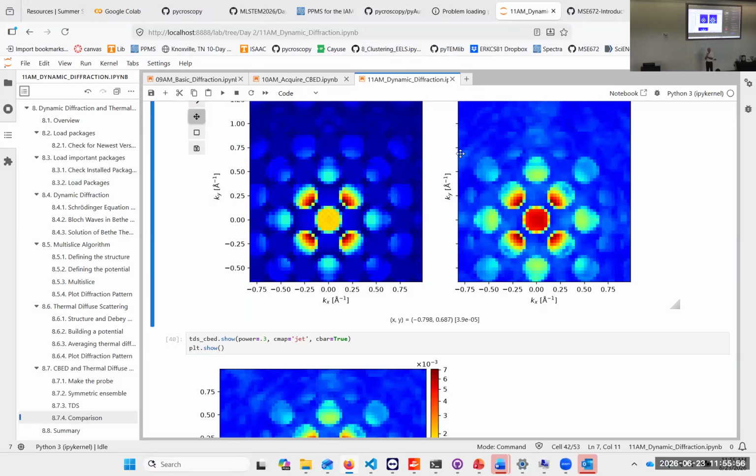At least in ABTEM, you can make it very, very sophisticated. You can use potentials from density functional theory. You can have that calculated, and then with molecular dynamics, you calculate the phonon dispersion, and then you can get that extremely close and see which kind of things contribute most, because you can switch it on and off in the computer. So that's the advantage of that. And that's what we do.